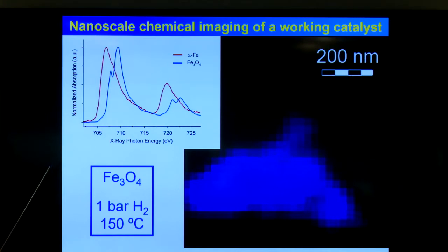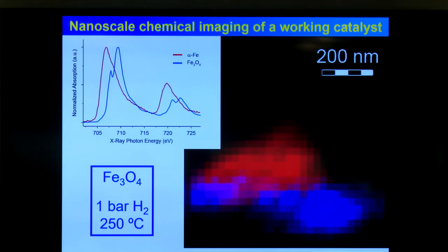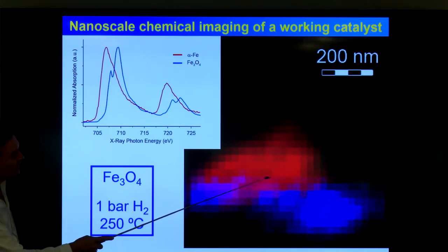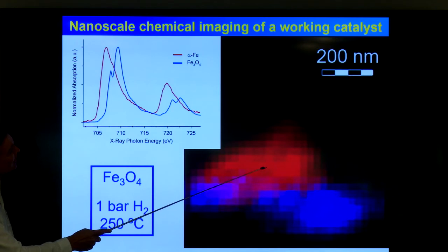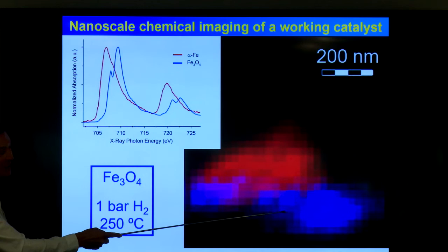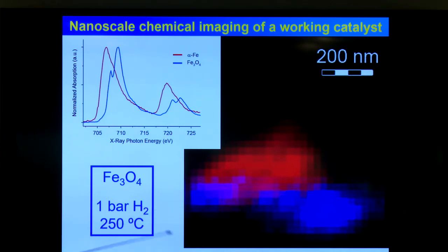And then we heat the sample in hydrogen and reduce it from Fe3O4 to iron metal. Because this is what we see in every sample, not only in this reference sample, but in all the catalysts. If we are somewhere halfway, we always have a situation like this, that some part of the sample is already completely reduced, and the other part, which is 100 nanometers away, is still completely oxidic. So the reduction, at least in these particles, was completely inhomogeneous.